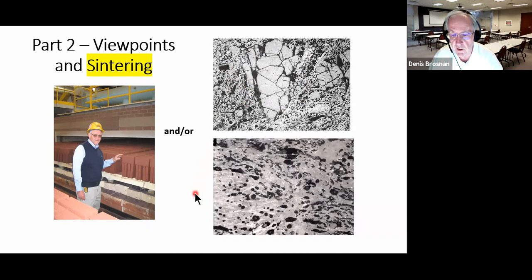If you go to a little bit higher magnification, then in fact, we can see the black pores again, but we can see a gray continuous phase, which is the glass that was formed in partial melting of the brick in firing. Not total melting, but partial melting, just a small percentage of glass. And within that glass, there are white streaks, and the white streaks are hematite, okay, that are reflecting the light visually from the macroscopic view, which John Dowdle is looking at. He's looking at a red brick. But when looking on a microscope, we're going to see a white color where the hematite is located, the red iron oxide.